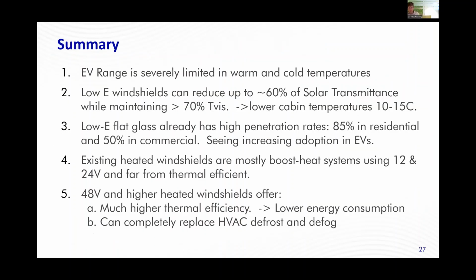So in summary, EV range is severely limited in warm and cold temperatures. Showed a couple of the different studies that are out there that show that. And the further you get away from ambient temperatures, the larger these impacts are. Low E windshields can have a big impact in warmer temperatures. They can reduce up to 60% of solar transmittance while maintaining that visibility transmittance above 70%. And it can have a significant impact on lowering cabin temperatures in the summertime.